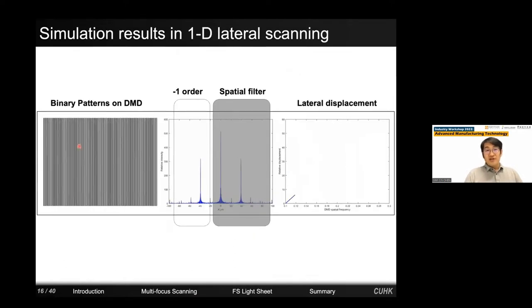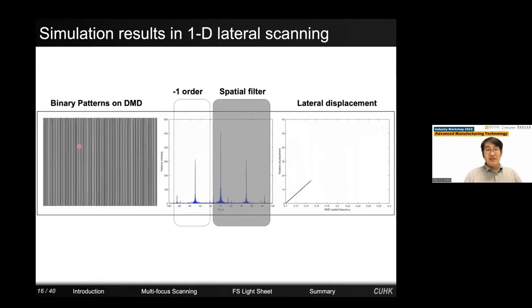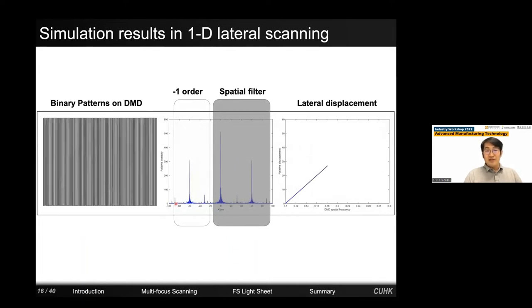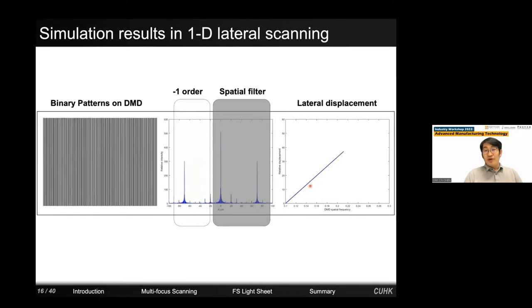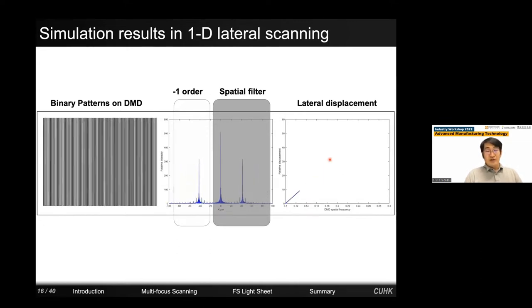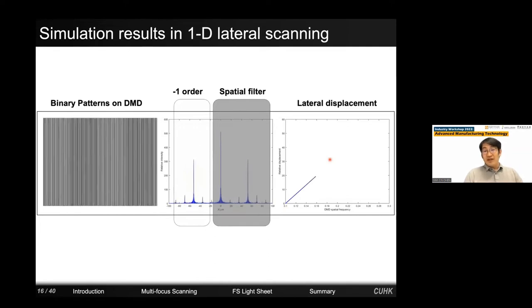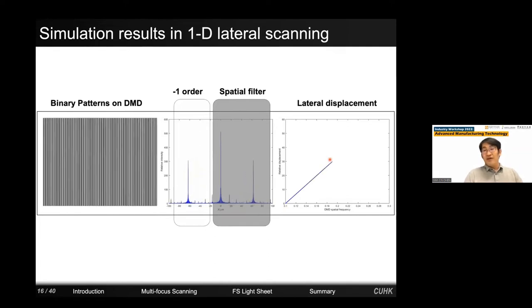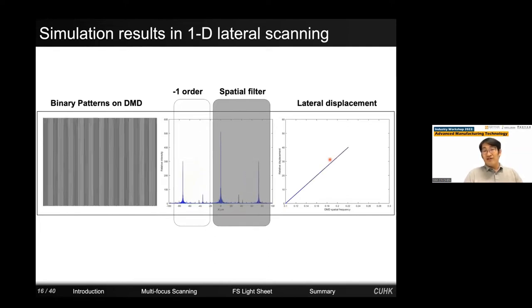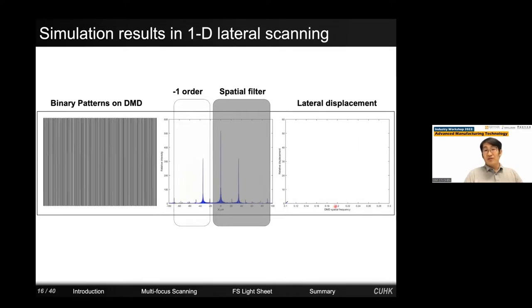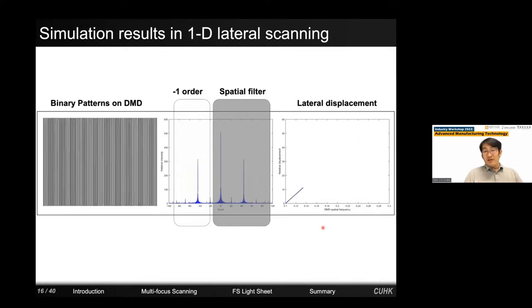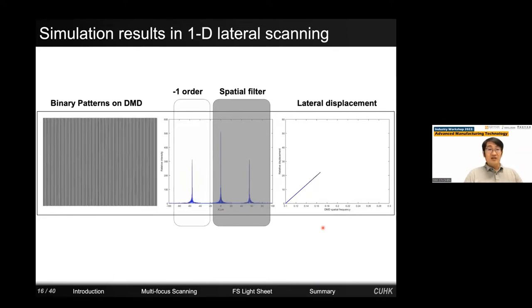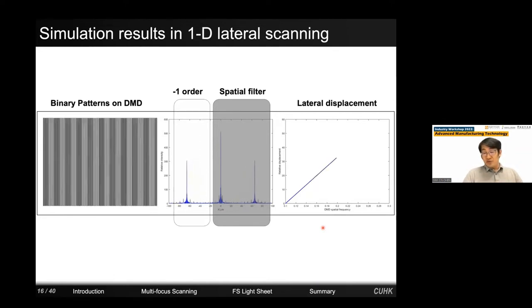So here we show a simulation of varying DMD patterns. As you can see, as the spatial frequency moves, the focal point moves as predicted. So based on our calculation under a 40x objective lens, we can quickly control the focal point in the axial direction for about 500 microns and laterally for about 200 microns, with an accuracy and minimum step size of about 100 nanometers, which is sufficient